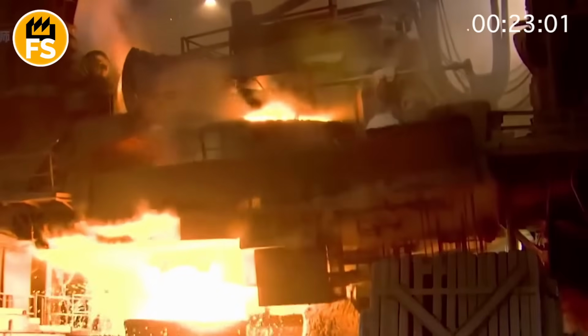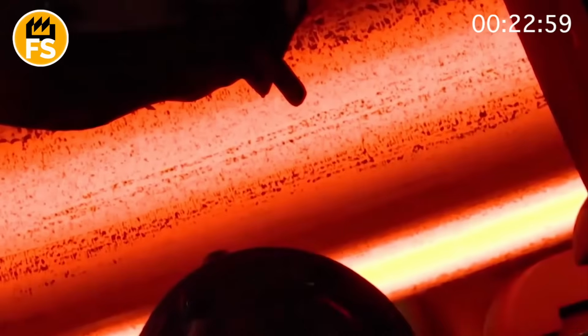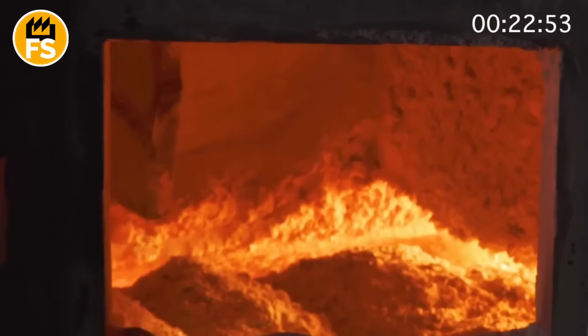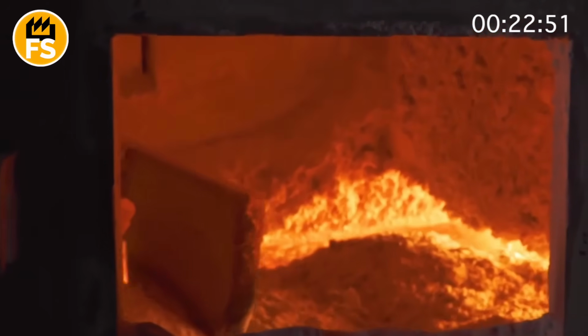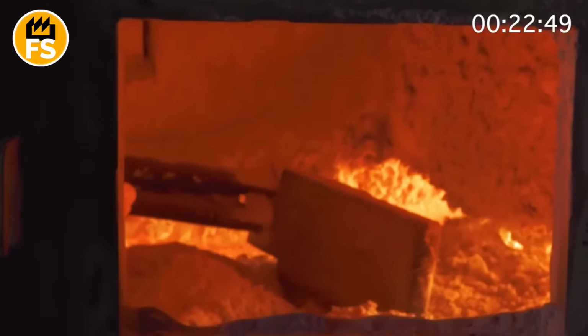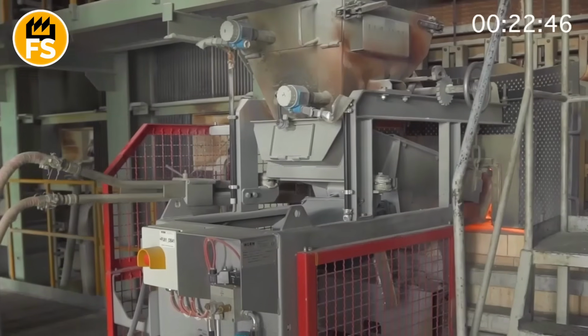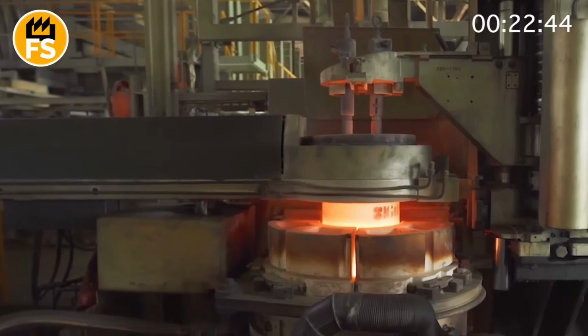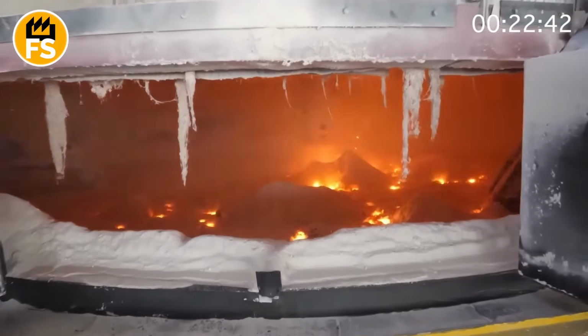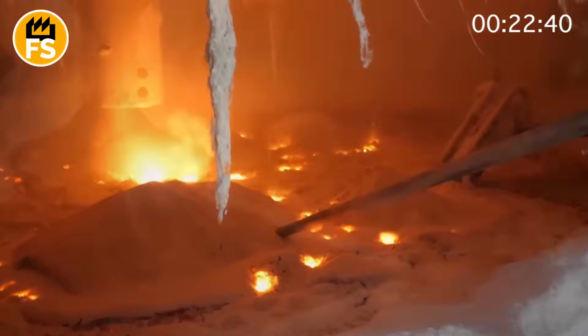Furnaces typically have a volume of 5 to 10 tons, and one such furnace can produce up to 300 or even 500 cast cylinder heads per shift. One shift lasts 8 or 12 hours. The production flow is set up so that the molten metal is continuously supplied for casting, so even 15 or 20 minutes of downtime can cost the enterprise thousands of dollars due to lost pace and cooling of the material.